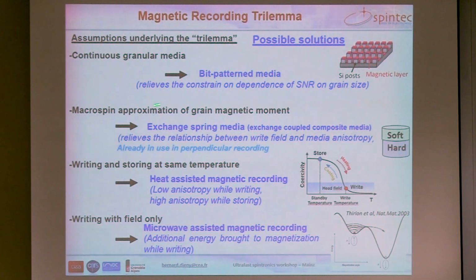Then another thing that we can do, instead of using only a hard material like a cobalt chromium platinum alloy as the media, is to couple on top of each other a soft magnetic material with a hard magnetic material. This is called exchange spring media. The idea is that the hard material provides the stability of the magnetization, but the soft material helps to nucleate the reversal of the magnetization. This allows simultaneously a good retention of the media together with a not so high switching field. And this is actually in use already in perpendicular recording.